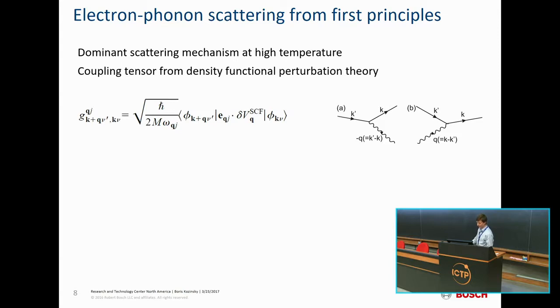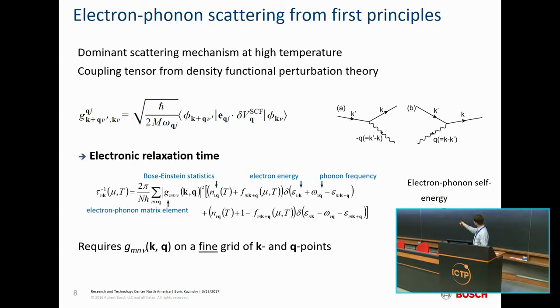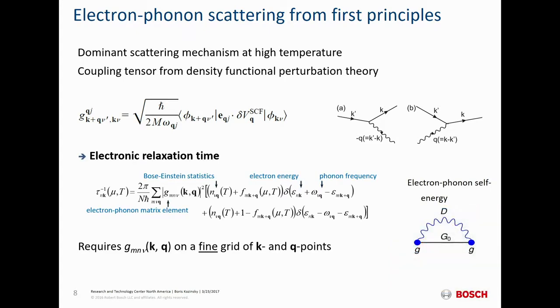And the main transport-dominating mechanism at the higher temperatures where thermoelectrics really operate is electron-phonon coupling. So the idea was to try to estimate the lifetimes just from the electron-phonon scattering matrix. And then from the Fermi golden rule, you could write down the lifetime as a quantity that depends on the actual mode and the electronic state, and count all the scattering events and add them all up in first order perturbation theory, and then compute the lifetime.